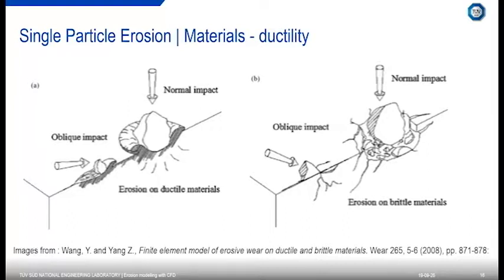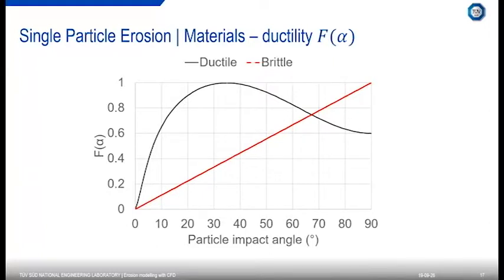So we can simplify this and represent it by a simple graph. So here we have, on the black line, the ductile response, and then the red dashed line, we have the brittle response. On the x-axis, we have the particle impact angle going from 0 to 90 degrees, where 90 degrees is impacting it directly onto the surface, and below that is at an angle parallel to it. The f of alpha is our function, our ductility function, 0 being the best case, 1 being the worst case. So you can see with ductile material, typically between 20 and 50 degrees is the worst case scenario, where brittle material is typically the worst case scenario at 90 degrees.